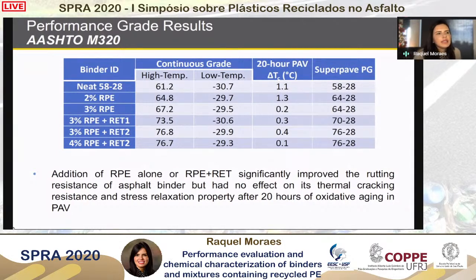You can see here that in comparison to the neat binder, we see an increase in the high temperature PG, sometimes by 2 or 3 grade bumps, depending on the percentage of the recycled plastics that is added. And on the low temperature end, we see no change in the performance grade in terms of the PG classification. And as you can see, the continuous grade was very, very close. So the major effect of the recycled plastic is the stiffening of the binder, which is indicated by the high temperature performance.